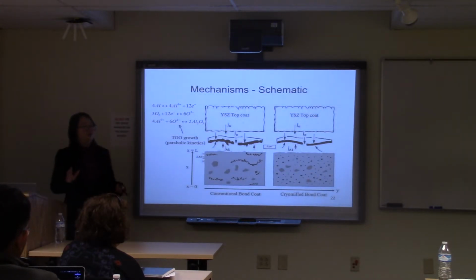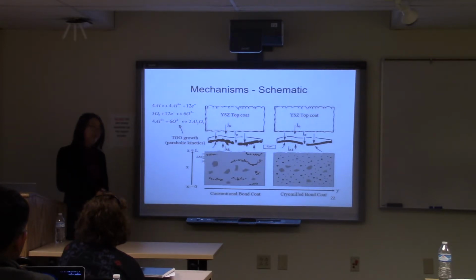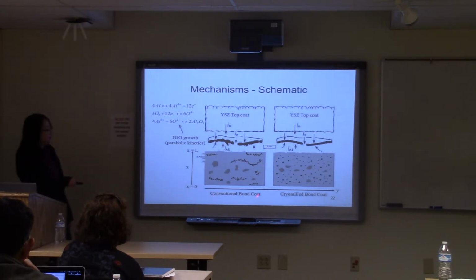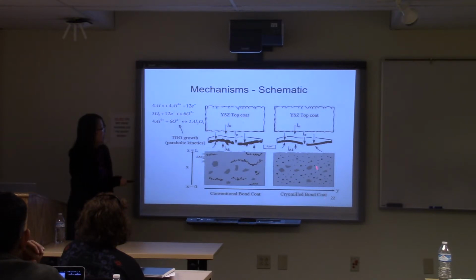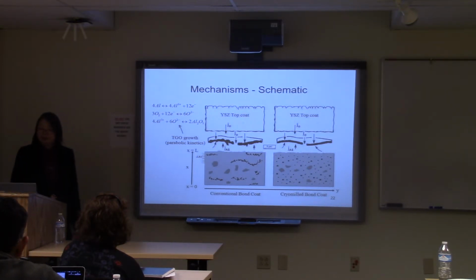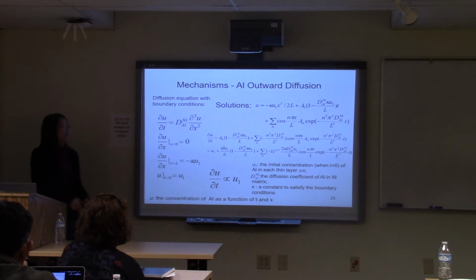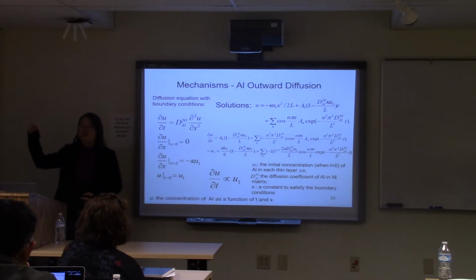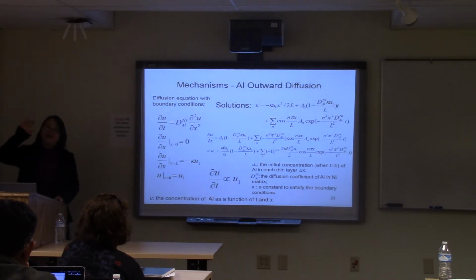So then I really want to develop mechanisms for how the microstructure gives you the final growth of the oxide layer here. So schematically showing you the key features between the conventional bond coat and the nanostructured bond coat. Because those dispersoids are rich in aluminum, which is the key element for you to form the oxide, I modeled this by setting up the boundary conditions and solving the diffusion equations. I'm not going to go into detail about the mathematics, but we came out with a solution: the diffusion rate of aluminum is proportional to the initial aluminum concentration at each layer, where I can divide the bond coat into very thin thicknesses to analyze this.